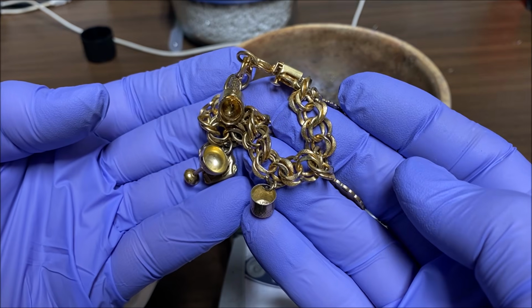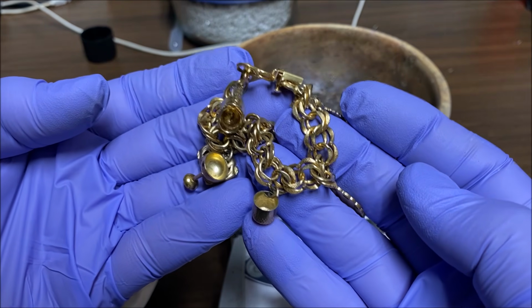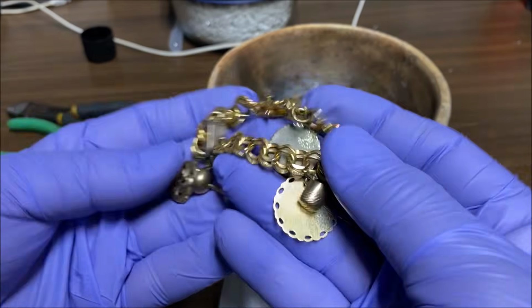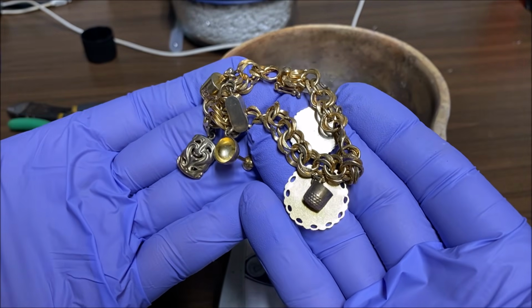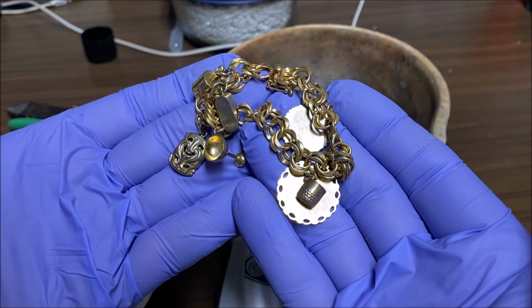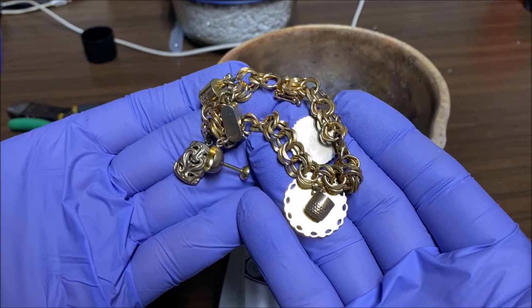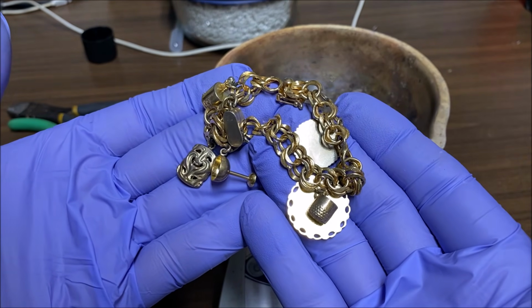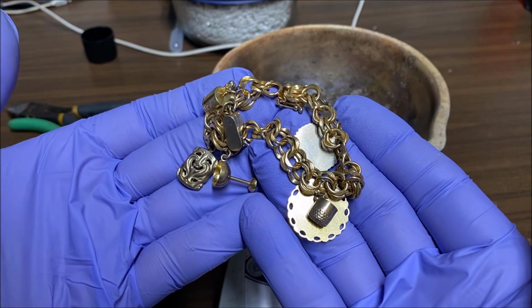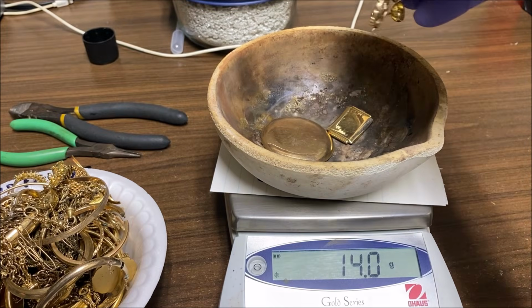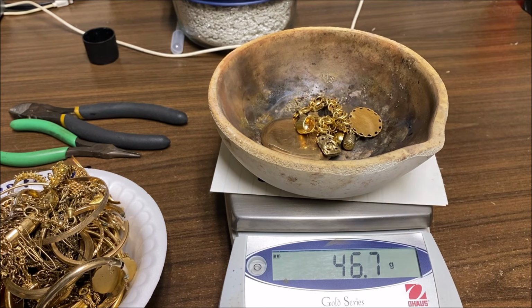Gold filled material will yield about 2.5% to 3% pure gold, which means for every 100 grams of gold filled scrap, you should get 2.5 to 3 grams of pure gold. Let me see how much this thing weighs. That's 14, and we got 46. So what's that? About 30. That's about a gram of gold right there. So that thing's worth $70, because a gram of gold right now, pure gold, is about $70.